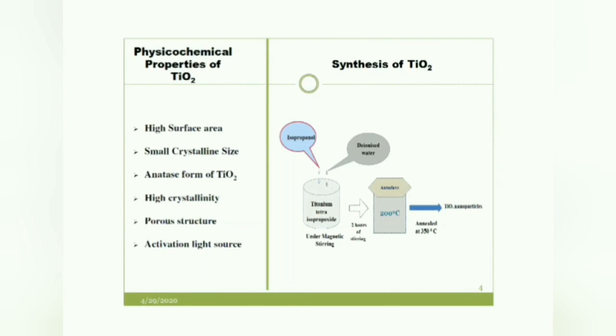And apart from that, the small crystalline size means it can easily penetrate, okay? And also the anatase phase, which is a highly good photocatalytic reacting substance, and also high crystallinity structure, and also your porous structure, activation by a light source. So these are some of the important properties why we prefer titanium dioxide nanoparticles. Our synthesis methodology comprises this.